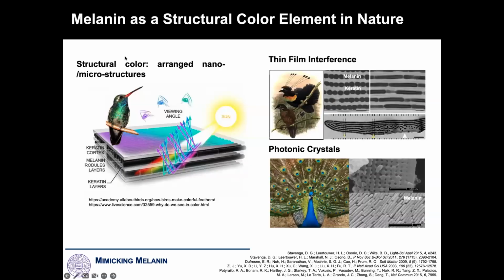I'll go back a sec, sorry. What's going on here? Essentially, one of the elementary features of this is a combination of low refractive index, high refractive index material. So in other words, materials that don't refract light very much and materials that do, combined with materials that absorb light very heavily. So the melanin is very black and the keratin is not. And you can see that in the electron scattering image, by TEM, but you get the idea about electron density.